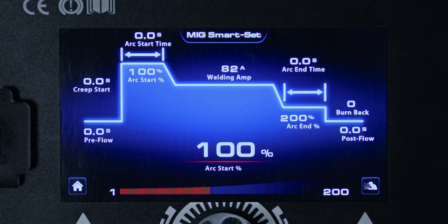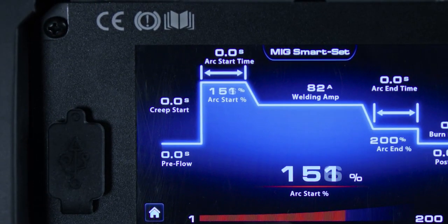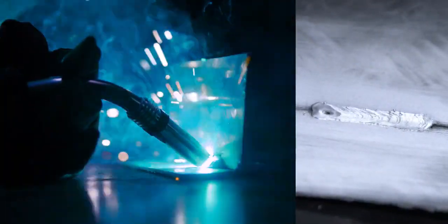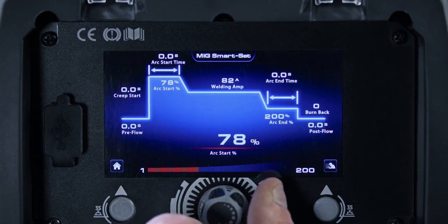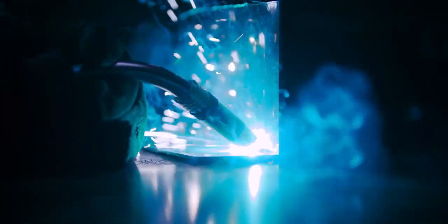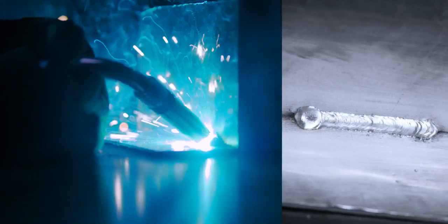You can set the arc start above 100% and the hot start will give you a boost in current at the start of the weld, eliminating issues with starting on cold metal and making welding on thicker materials easier. Set it below 100% and the soft start will help with edge arc ignition by starting at a lower current and ramping up when welding away from the edge.